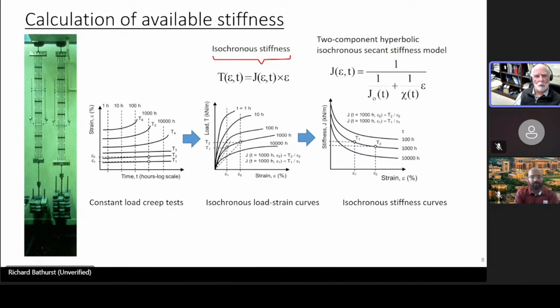We developed a model, a two-component hyperbolic isochronous secant stiffness model that has the equation that you see on the right-hand side. And one takes the results of constant load creep tests from the lab. You can develop from these curves, and this is a technique which has been around for a long time, so-called isochronous load strain times for different durations of load. From these curves, one can construct stiffness versus strain curves for different isochronous times or load duration times. And these stiffness curves are well quantified using this hyperbolic model that you see here.